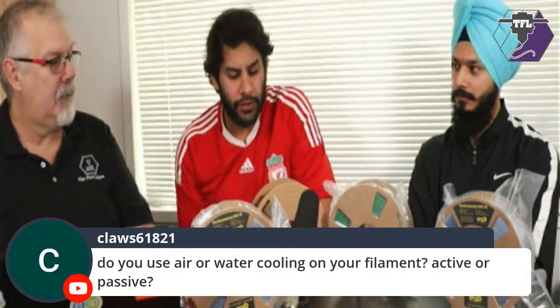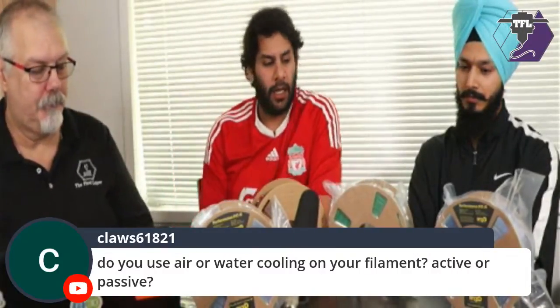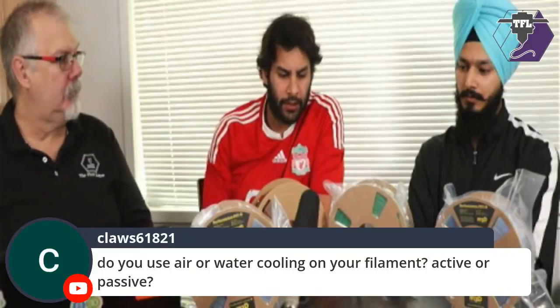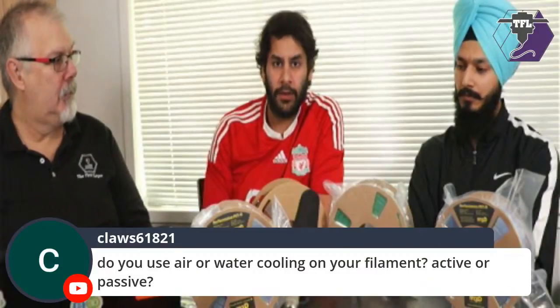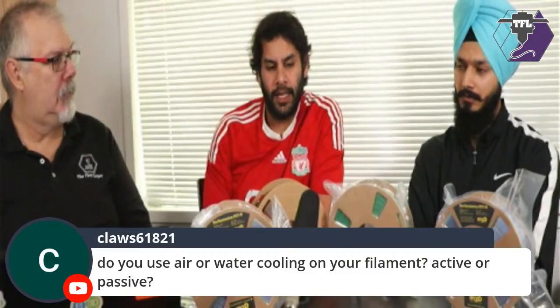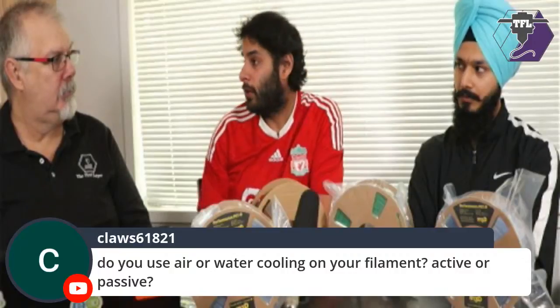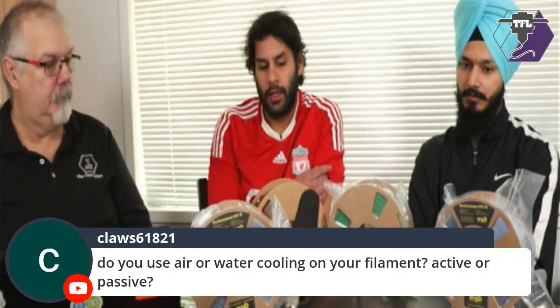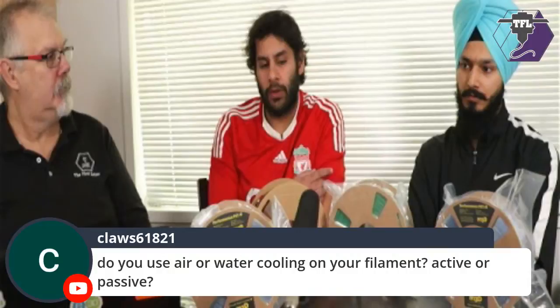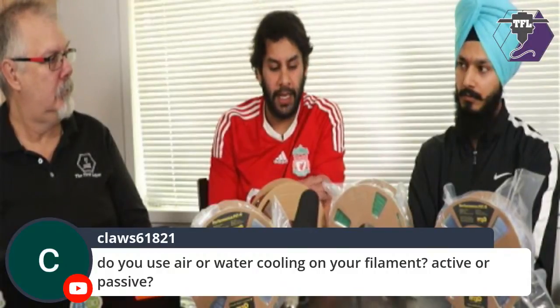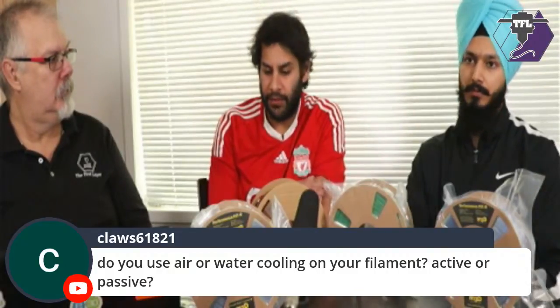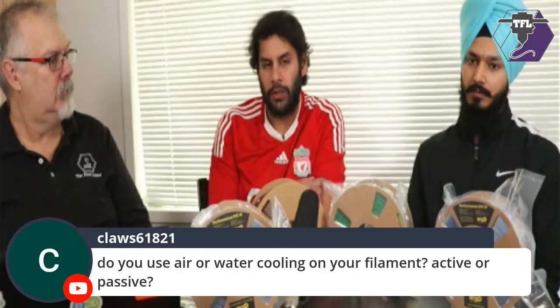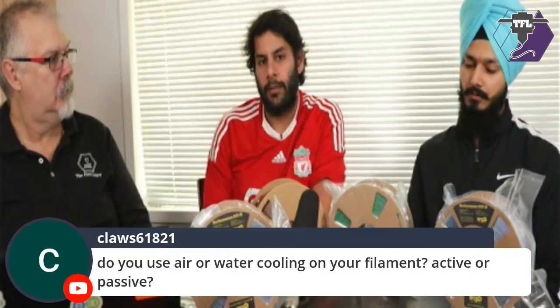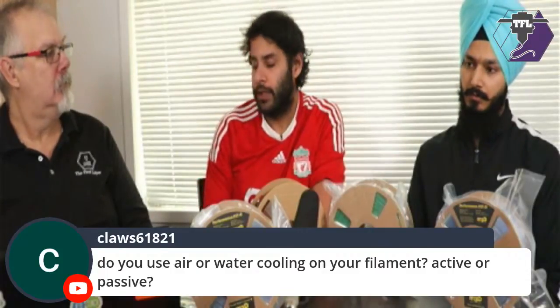Yeah, that's a great question. So it depends on what filament we're making. Without giving away too many trade secrets, it depends on the heat capacity of the material. And if your heat capacity is quite high, you can use water cooling, which is what we do. It's active water cooling. So we heat up the water to a specific temperature to make sure the material as it comes out of the extruder maintains its diametric tolerances.